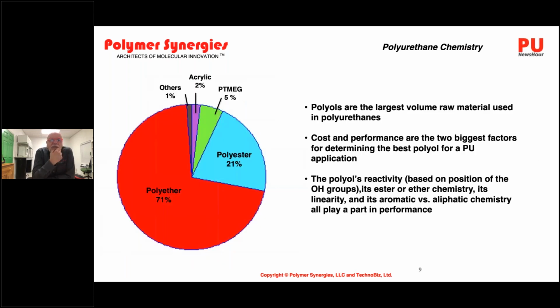When we talk about polyols, they are the largest volume raw material used in polyurethanes. Okay, so cost and performance are the 2 biggest factors for determining the best polyol to use in your application. And the polyol's reactivity, based on the position of the hydroxyl groups, whether it's an ester or an ether, its linearity, its aromaticity versus aliphatic chemistry, these things all play a part in the performance of the polyurethane. And as you can see, polyether polyols are the largest volume polyols used, followed by polyesters. Then we have polytetramethylene ether glycols, and then acrylic polyols, and all of the others account for about 1%. And those are going to include some of the bio-based polyols I'm going to talk about in a moment.